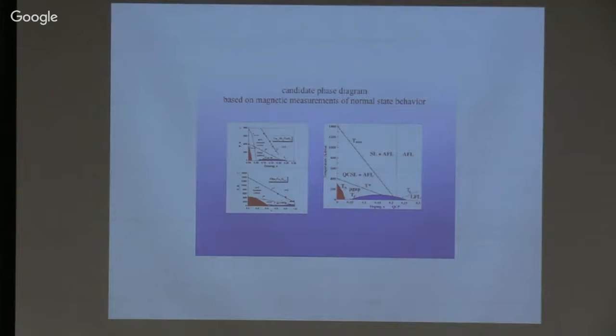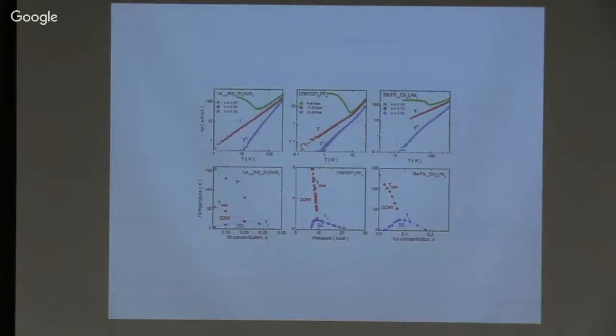And these are the kind of candidate phase diagrams that arise. I'll just show them there. You can look at the literature and find them in more detail. But they all suggest that what's going on in the normal state is a mixture of an anomalous Fermi liquid, that's the AFL, and either a quantum critical spin liquid of local moments, or at lower temperatures, they form the pseudogap state. And that has to be the starting point for any subsequent theories.